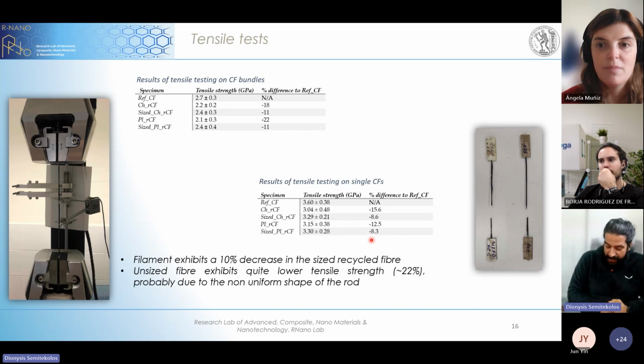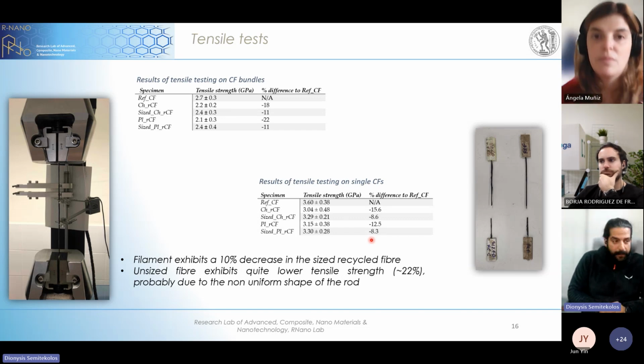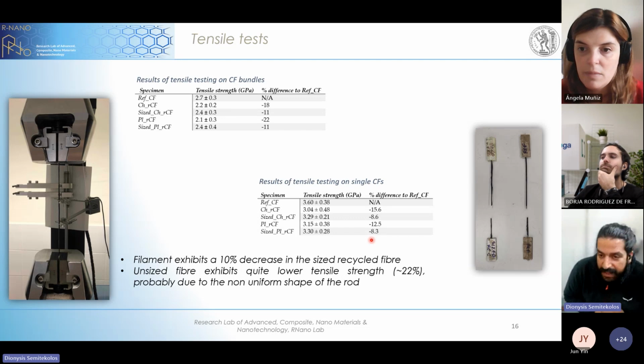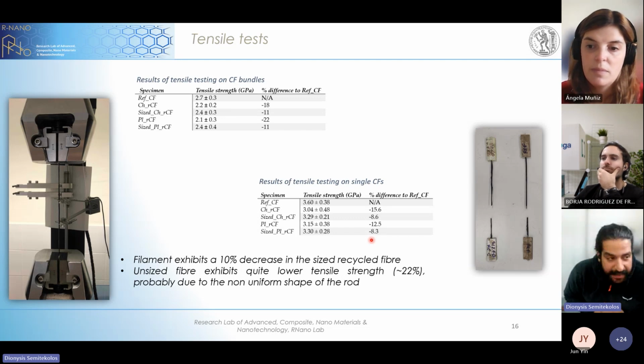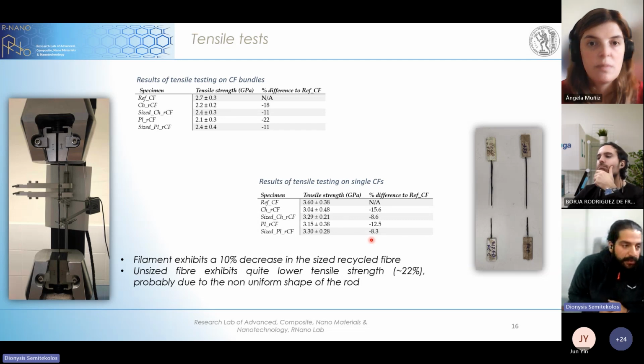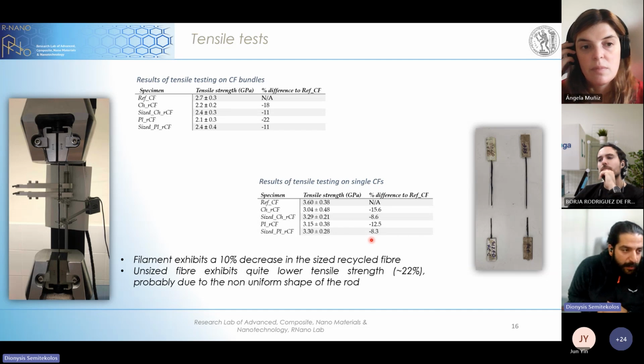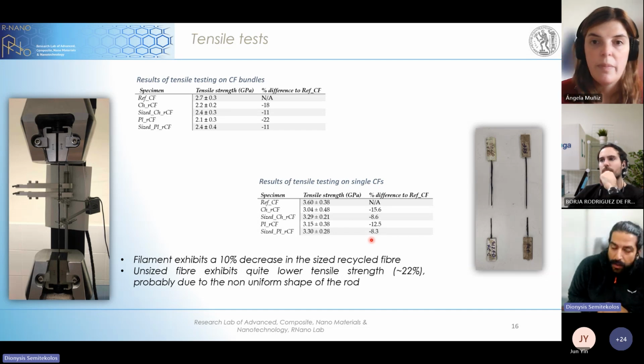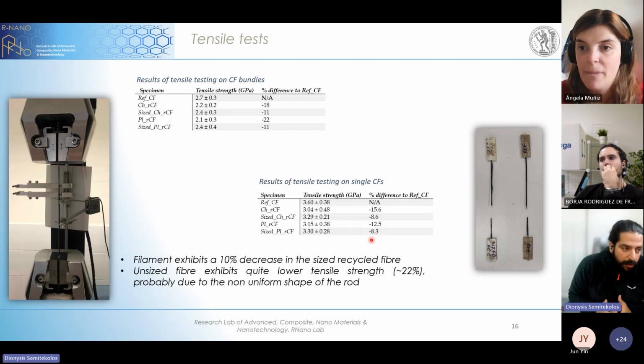So as Yoon said, the ideal would be to test the ILSS, interlaminar shear strength, or interfacial shear strength, and we plan to do this in the following months by a pull-out test with nano-indentation, or we're also going to make some composites and do a short beam test. With this test, we determine the ILSS. With a pull-out, we do the IFSS.